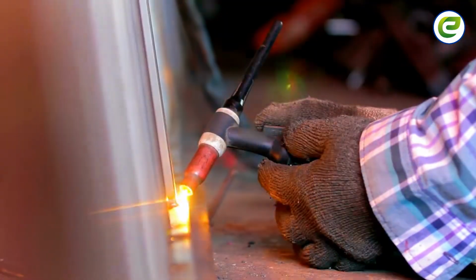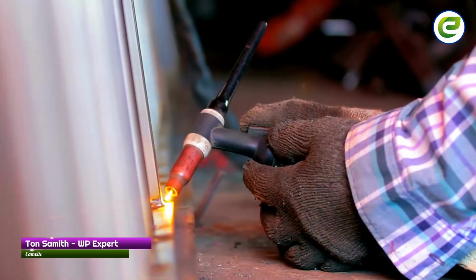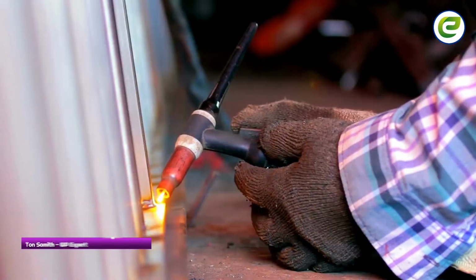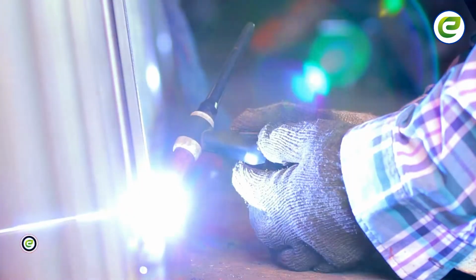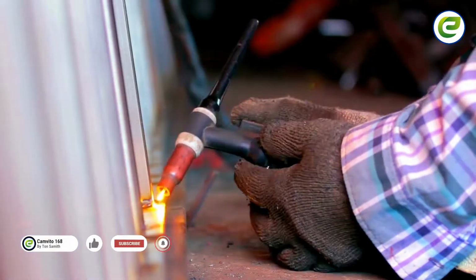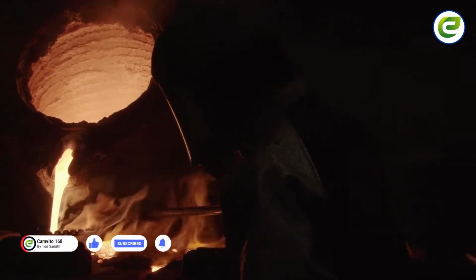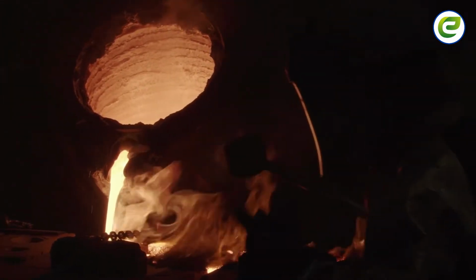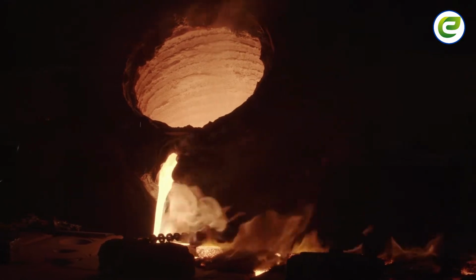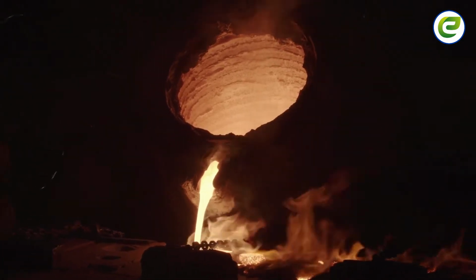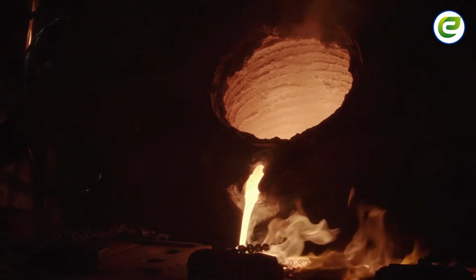In an attempt to achieve homogeneity, the initial product was removed from the kiln, forged, and again reheated with charcoal in the kiln. During the reheating process, carbon monoxide gas was formed internally at the nonmetallic inclusions. As a result, blisters formed on the steel surface, hence the term blister steel to describe the product. This process spread widely throughout Europe, where the best blister steel was made with Swedish wrought iron.